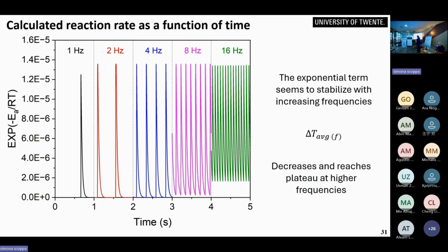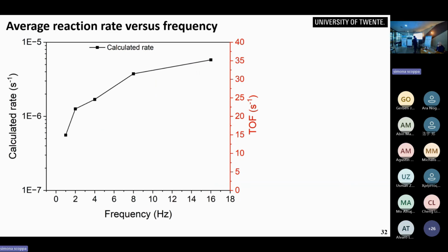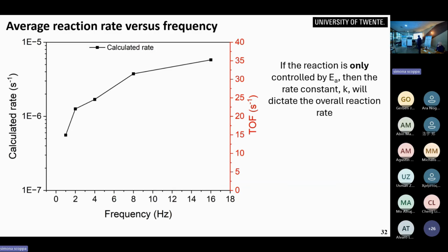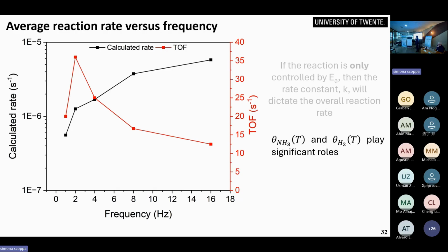So this is essentially my kinetic constant as a function of the different frequencies I use. And what you see, generally speaking, is that this number starts to go up as you go to higher and higher temperatures. So the calculated rate should go higher and higher as I go to these higher average temperatures. But in reality, when we calculate the turnover frequency that we measure experimentally, we see a very different picture. What you see is that the turnover frequency actually decreases as you go to faster frequencies. That's a very counterintuitive effect. You don't expect the rate to decrease with an increase in temperature.